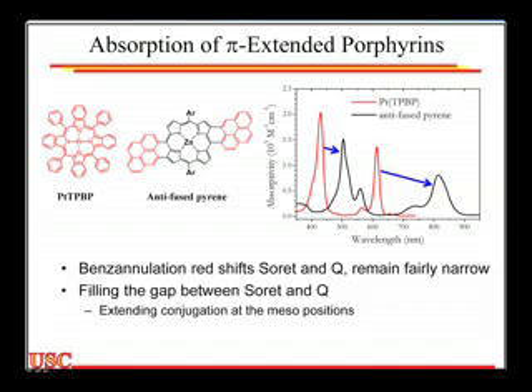So the good news is it means that the steric bulk that I built into this, just to keep it from being too insoluble, so this has dibutyl phenyl groups, which are what Ar is in these two cases, gives me enough of a standoff at the C60 that I'm still getting a good open circuit voltage.